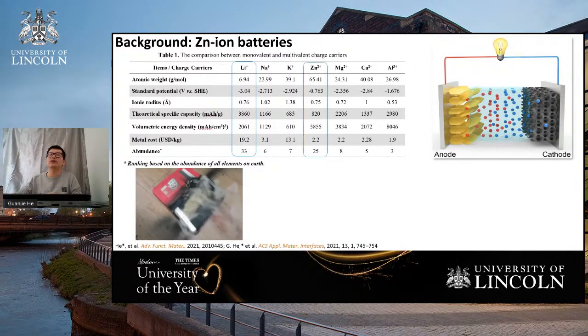In our group, we recently focus on zinc-ion batteries. If you consider the atomic weight, it is not that suitable, around 65. It is relatively heavy, right? But each zinc can provide 2 electron charge carriers. Also, the standard potential for zinc versus the standard hydrogen electrode is -0.76 V, which is suitable for aqueous energy storage applications. The volumetric energy density of zinc is good, and especially the metal cost is very cheap, just around $2 per kilogram. And if we use zinc directly as the anode, it can work in aqueous electrolyte.